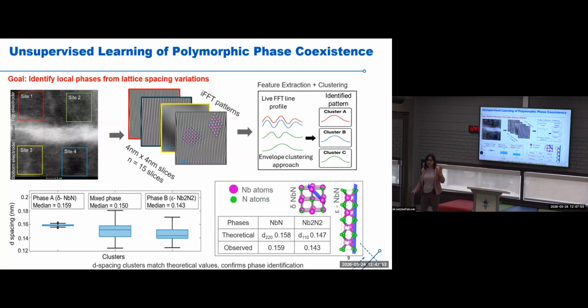So what it shows is the coexistence of 2 different phases, which was totally missed by the conventional characterization, because we saw TEM, oh, it looks all good. We did APT. APT doesn't give the phase, but composition. But this was missing. So what we are seeing now is that there is a co-phase existence very locally, which cannot be captured with the conventional way.